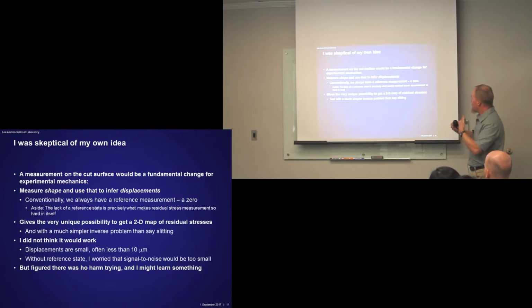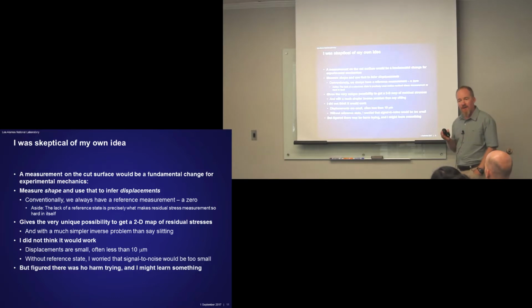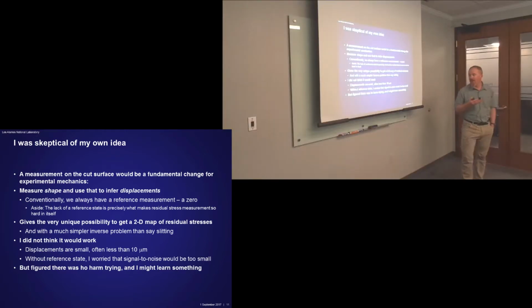If you do that, it can give you that 2D stress map, so I knew that it could be quite powerful. And it's a much simpler inverse solution than we use for slitting too. So you can kind of double up with benefits if it worked. The displacements are often small, less than 10 microns, and we have no reference state. So I was quite worried that signal to noise would be too small, and we'd never see those displacements. Figured there was no harm in trying, and I might learn something, so I thought I'd give it a try.